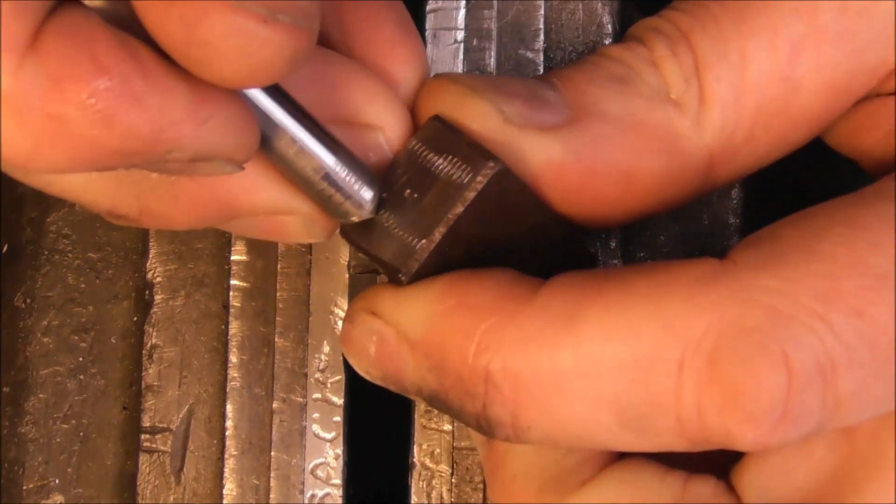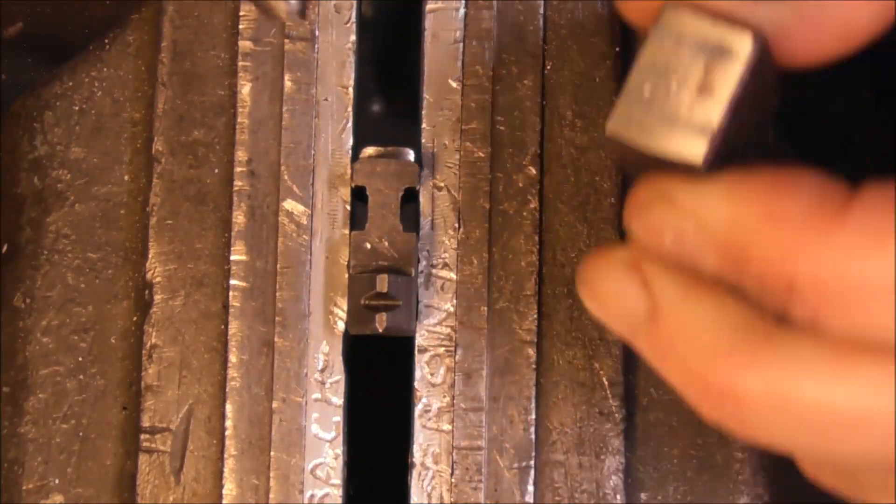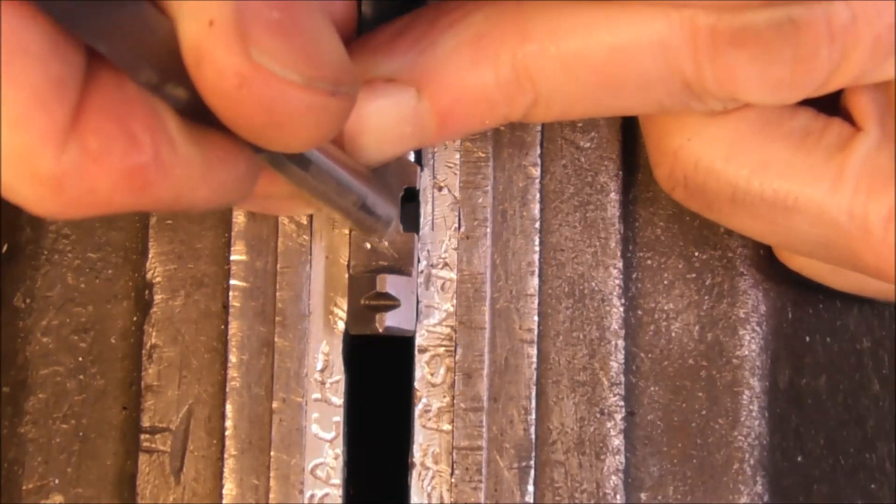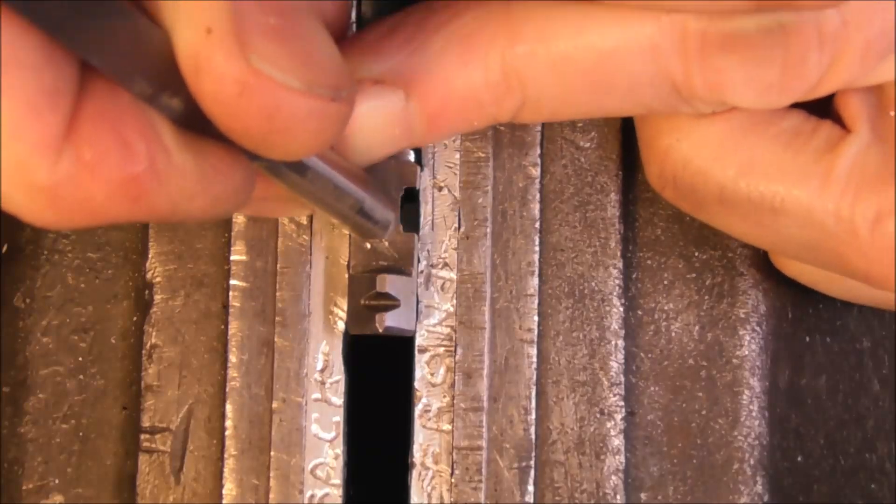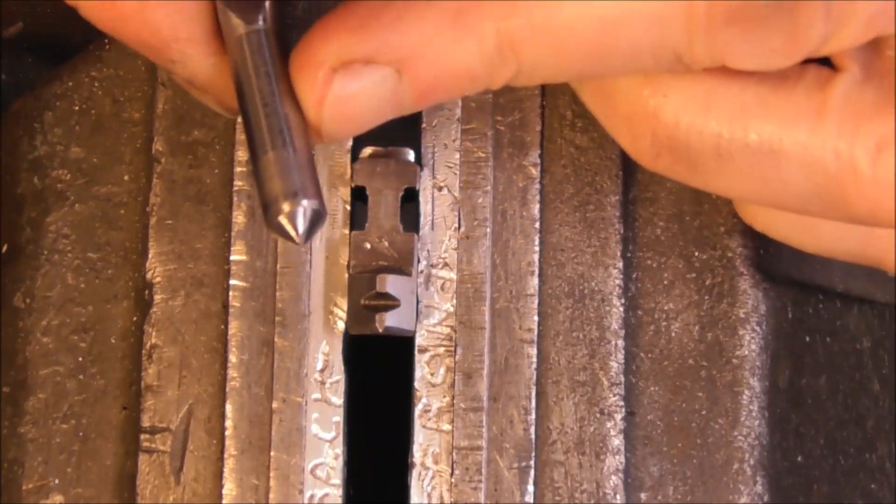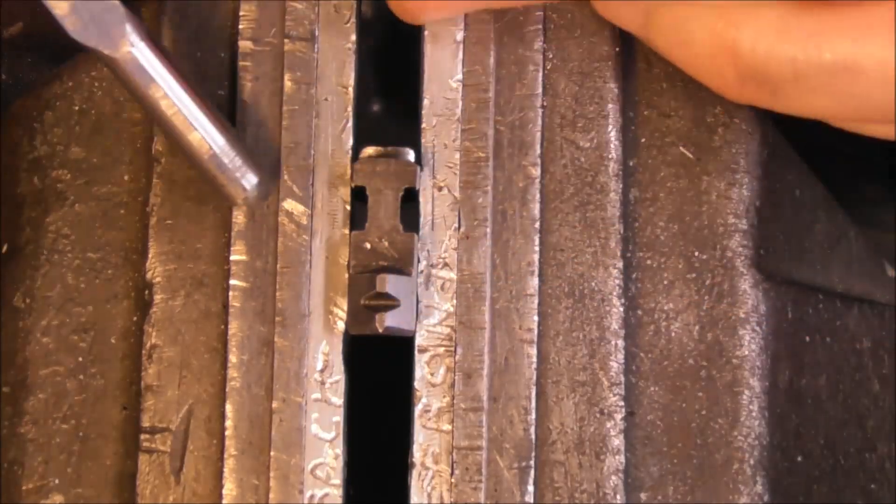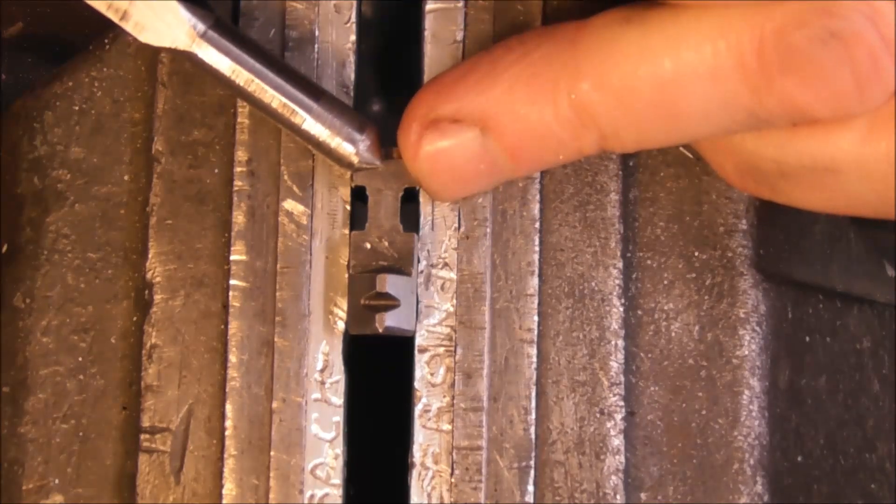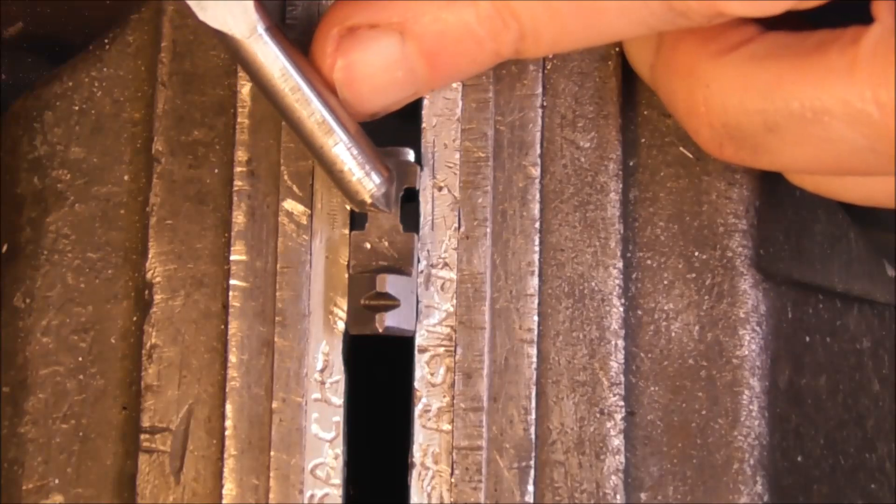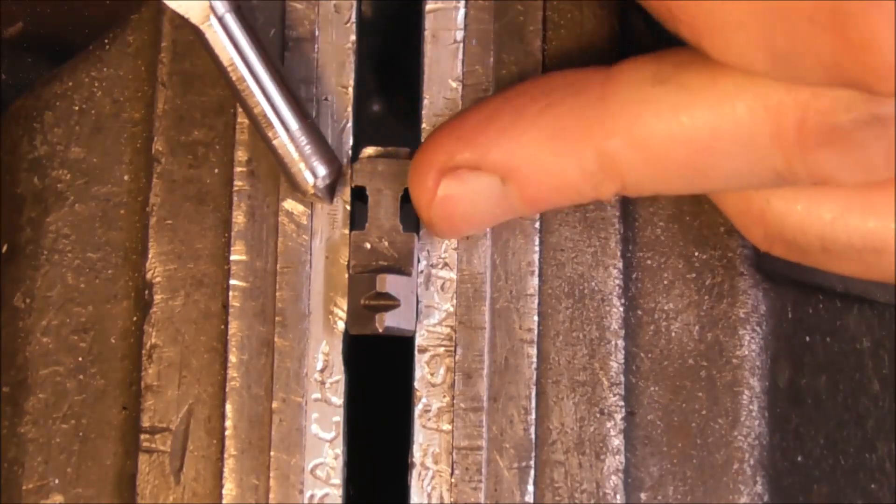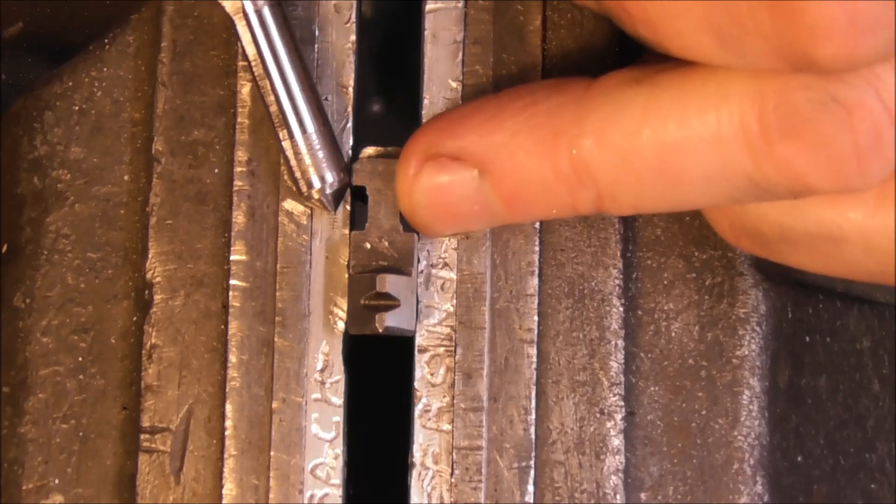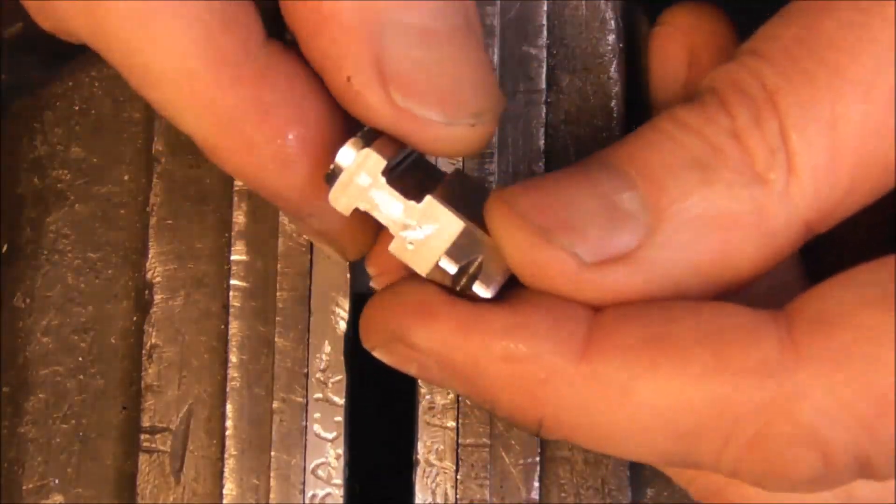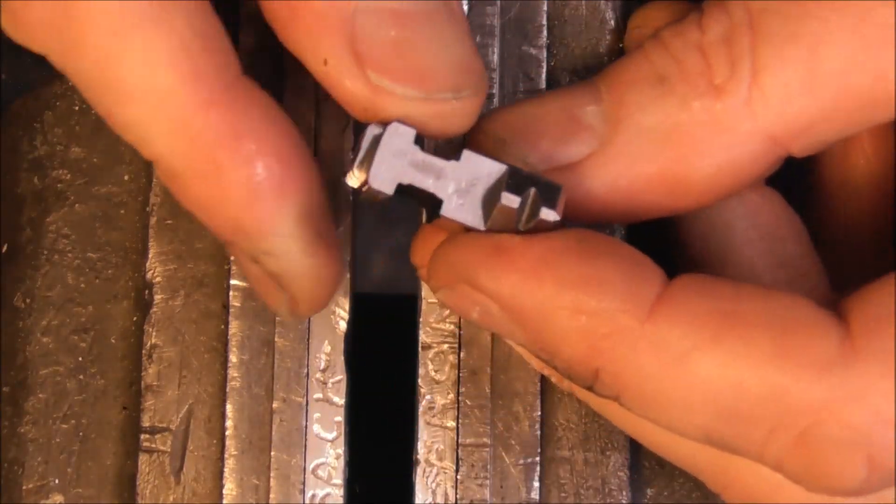But I can't scratch down at that depth that I've ground down below the case with this P20 steel, which is around about 30 Rockwell C. So that means that the jaw is at least 30 Rockwell C. I'm hoping it's a little harder—I'm hoping it's around 40, but it may only be about 30 Rockwell C, which is the hardness and toughness of a high-tensile steel. So the jaws are not as hard as you'd really like. They'd be better if they were case-hardened, but then I wouldn't be able to make these modifications.